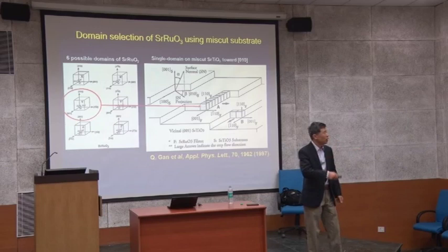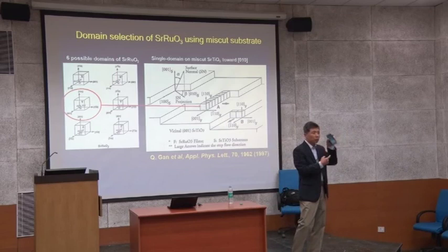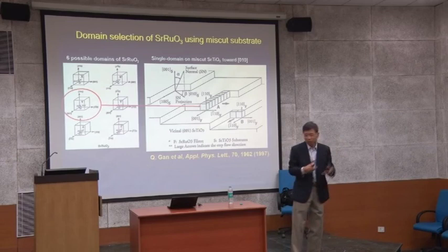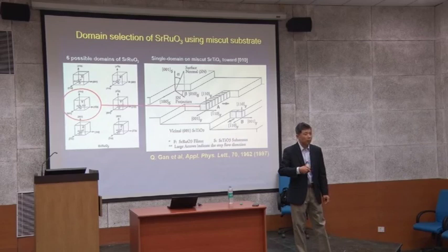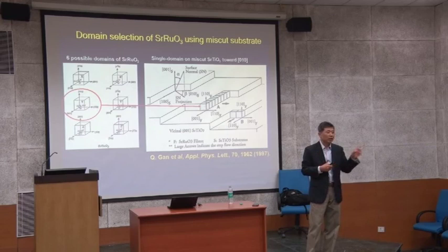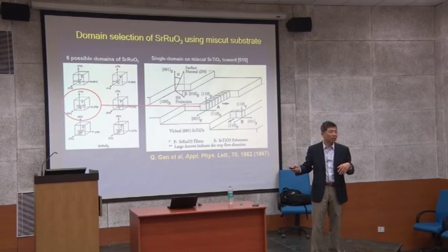Why rotate the phi angle? Remember yesterday I said phi rotation? When you do that, you know the surface plane, which direction, the 100 direction, when you align your sample. With respect to this alignment of the sample, we know which direction that is. So from this rotation, we know which direction the miscut angle is with the sample. Okay? I think I need to sit down and explain this, without drawing it takes time. Each sample alignment measurement takes time. In our lab, we have lots of papers on the wall, and you just use a marker, draw the line and measure which direction and miscut angle.